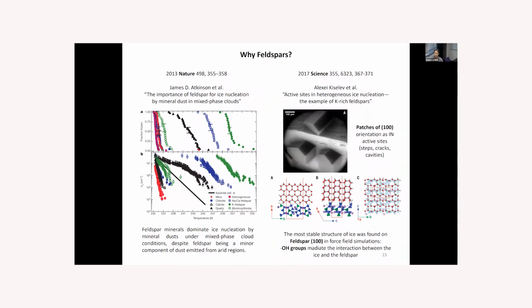And most recently, in 2017, in the Science paper by Alexei Kiselev, we could see that the ice crystals grow preferentially on the 001 face, and oriented preferentially on this face as a basal plane of the ice. Patches of the 100 orientation were seen as an active site in ice nucleation, and they are occurring mostly in cracks, steps, and cavities, on the defects on the surface. And it was also supported by the force field simulations, where it was seen that these are the OH groups that mediate the interaction between the ice and the feldspar and facilitate the nucleation.